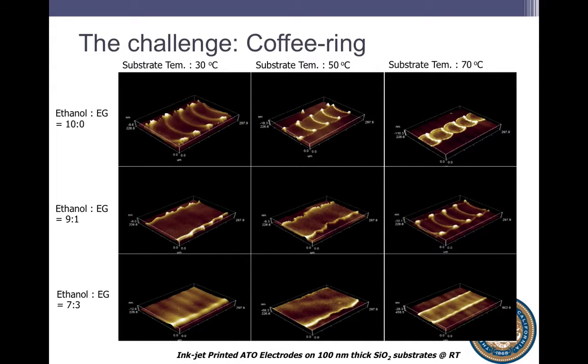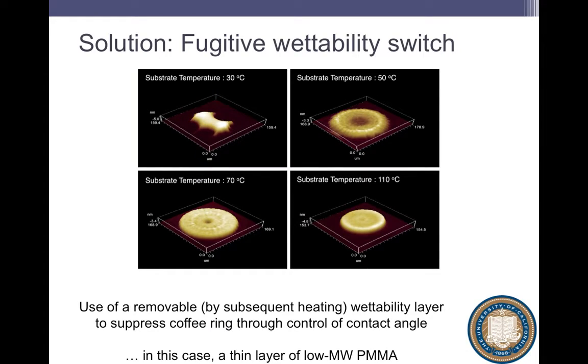And in particular, we use a technique which we call a fugitive wettability switch, which is, well, it's nothing particularly fancy. What we do is, it turns out, to prevent the coffee ring, one of the things you want to do is maximize contact angle hysteresis, which is the difference between the advancing and receding contact angles. One way to do that is to have nanoscale roughness on your substrate. But if we're printing on glass, we don't really have easy ways to induce roughness dynamically.